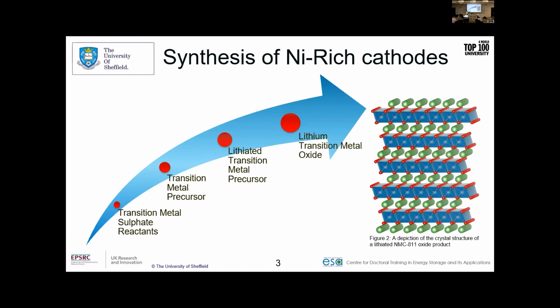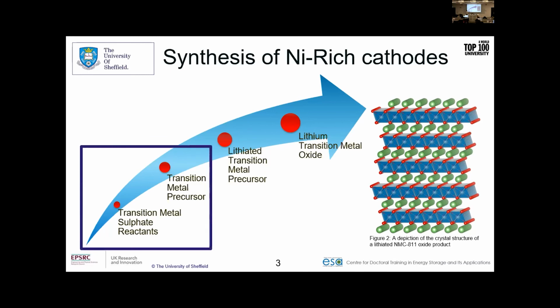So you can see we've got these sort of blue octahedral shapes which contain the transition metals, and then these green dots are the lithium ions. So this nice sort of layered sandwich structure allows lithium to go in and out nice and smoothly, causing minimal disruption to the actual structure as a whole, and that allows good rate capacity so they can charge and discharge easily and at relatively high speeds. But this talk will focus on this portion of the synthesis pathway to form the precursors, because that's a lot of the chemistry, a lot of control and balance is needed to form the right particles moving forward.